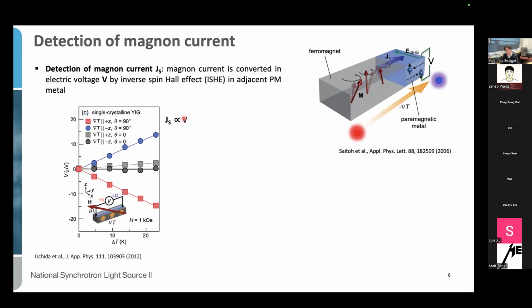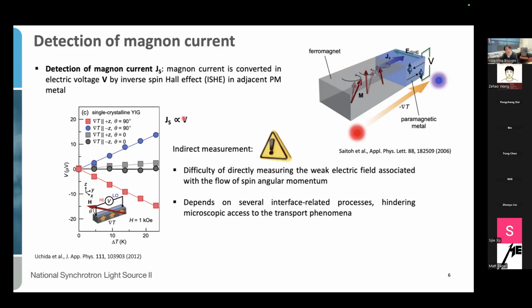So while this is a pretty effective method to measure and to deduce the existence of the magnon spin current, I need to warn that this is an indirect measurement. And it is actually the most convenient approach, because as an alternative, it is just simply too hard to measure the direct signal that comes from the weak electric field associated with the flow of spin angular momentum. So it's simply not possible to macroscopically measure a magnon spin current directly. But also, we need to be aware that this indirect process actually relies on several interface-related processes and conversion phenomena as well, which basically hinders the microscopic understanding of the magnon transport process itself.